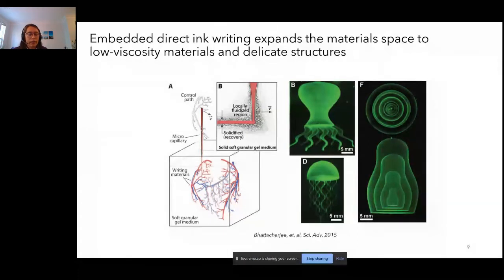Because these materials have a yield stress, they'll behave like a liquid when the nozzle is moving through them, and that'll allow the nozzle to move. But they'll behave like a solid after the nozzle has left, so they'll hold the form of whatever you printed. This means that we can expand the available material space into low viscosity materials, and we can print thin-walled structures and delicate structures because we don't have to worry as much about the properties of the ink when you have that extra support available to you. After you're done printing, you can remove these parts from the bath either by scooping them out or using dissolution in a buffer.